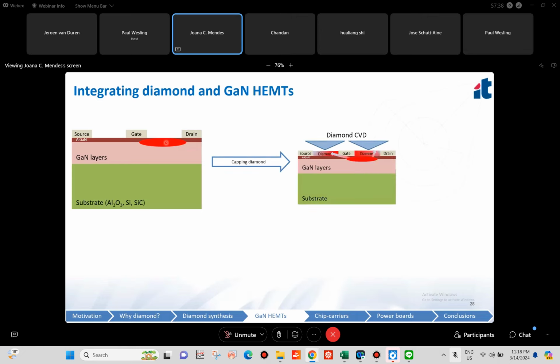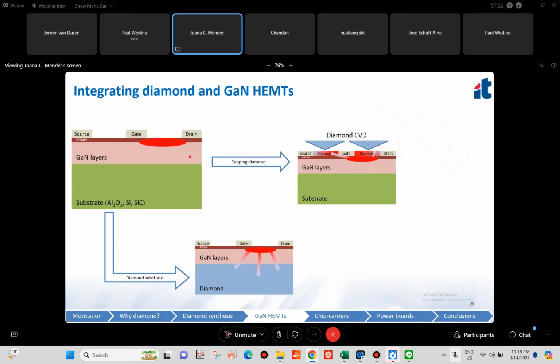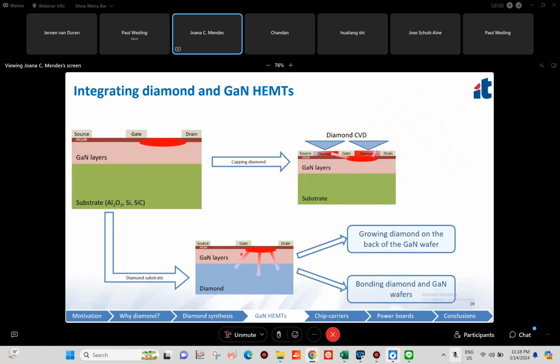Well, we can simply cap the devices with diamond by growing diamond on top of the chips. And here the heat will flow through the AlGaN layer to the diamond heat spreader on top. Or we can also replace the substrate with diamond. And we can do it two ways. We can either grow the diamond on the back of the gallium nitride wafer, or we can just bond the diamond and gallium nitride wafers.